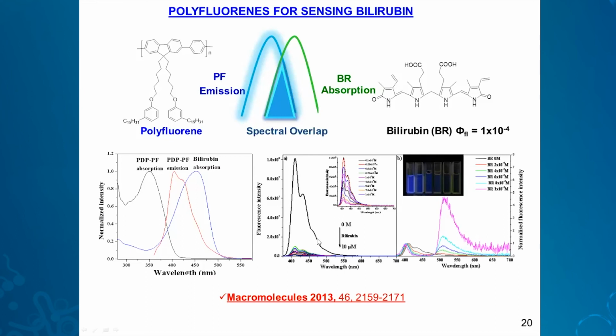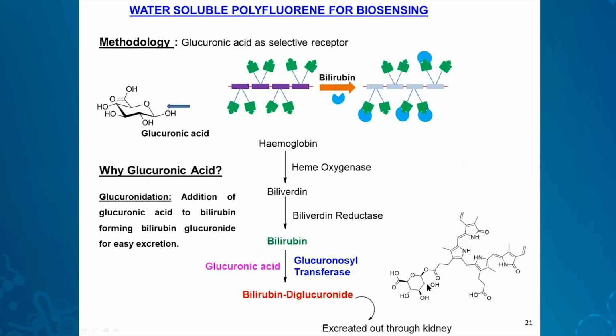So this is the emission from polyfluorene. The moment you add bilirubin, the emission is quenched so much. Actually, bilirubin is a very faintly emitting molecule. Its fluorescence quantum yield is shown here. It is a weakly green emitting material. So if you normalize the spectra, you can see that the green emission of bilirubin is coming up. The blue color of polyfluorene disappears and the green of the bilirubin comes up. So this was our initial work and this was done in THF.